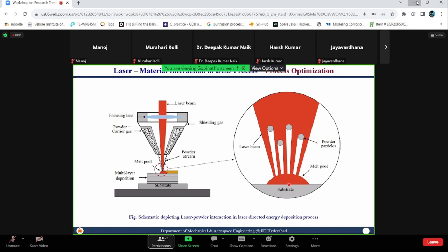See, complex or industrial grade systems typically modulate laser power. But at lab scale, it is tough. So you can control what we call scan speed. Now, what we have done is increase the scan speed a little bit. The moment you increase the scan speed, energy input per unit length will reduce. So again, from this state, you can come back to this state. Here again, you see it dropped down to the minimum detectable temperature.